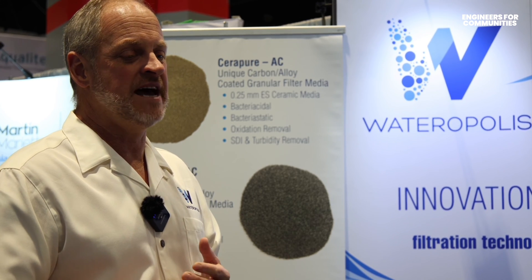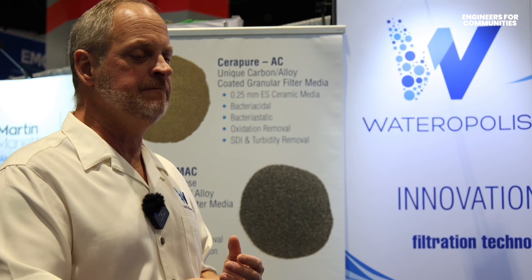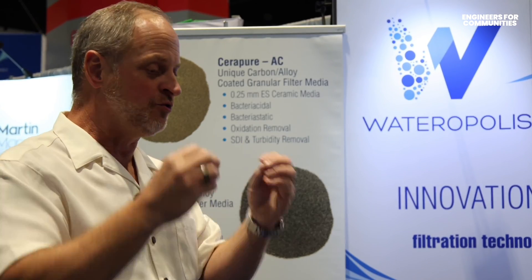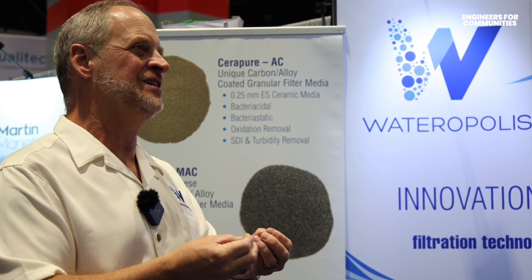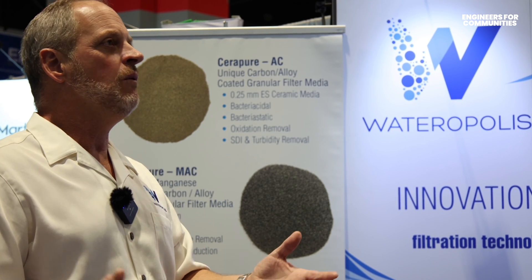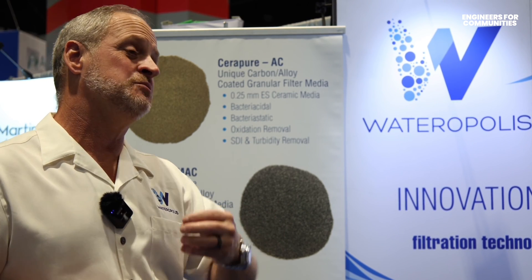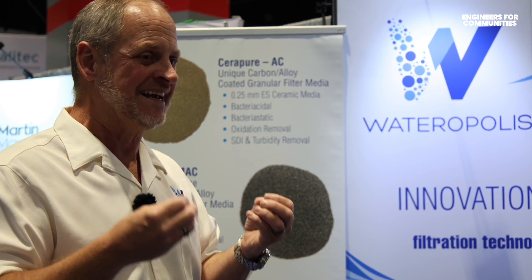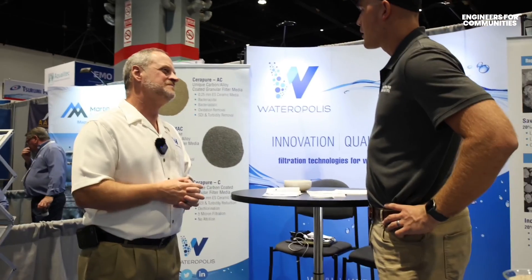Some clients take an inert ceramic and feed permanganate, and eventually that permanganate chemical creates a coating on the media. Eventually they can shut the permanganate off because they've put an MnO2 coating on the media. Then someday they replace the media — which they probably didn't need to do — and wonder why their system isn't taking out manganese anymore. You've lost that coating. So sometimes we go into filters and intentionally create that coating to help create a catalytic surface for taking manganese out.